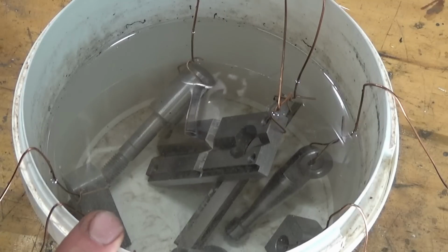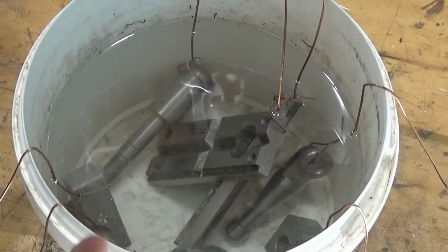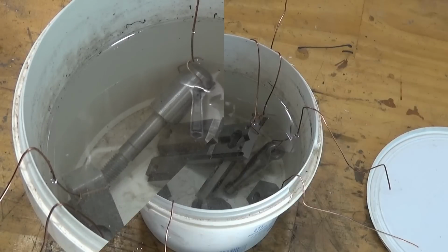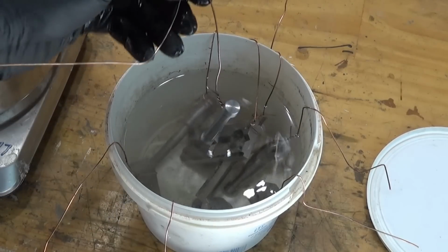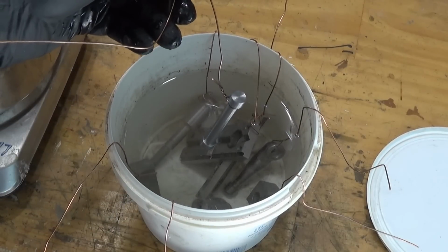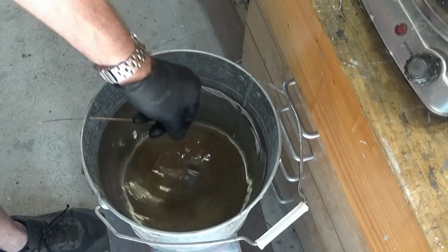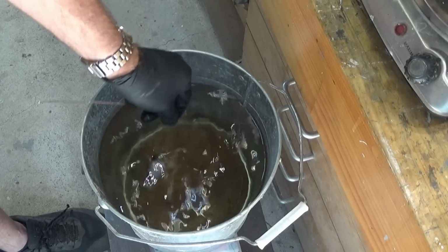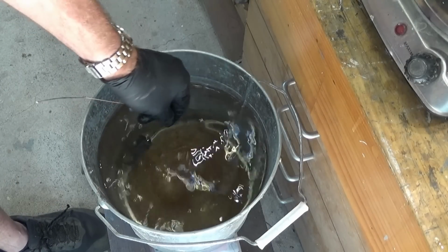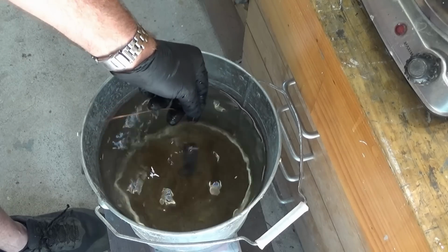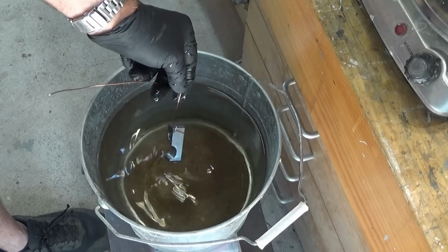While that Metex M is doing its magic, there's a stream of very fine bubbles coming off the part, so you know it's actually working. Okay, these come out now and they go into a cold water rinse. Okay, these parts get swilled in clean water, and from there they go into a pot of boiling water. They'll sit in there for about 1 minute just to preheat the steel parts.